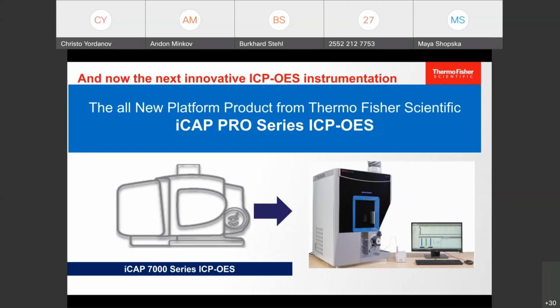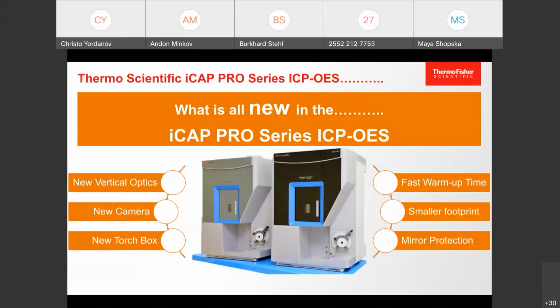And it's not evolution, this time it's revolution, because more or less all the parts inside of this instrument are new. We have a completely new optical tank. We have a new camera that's coming from astronomy. It's installed on satellites for astronomy research. We have a completely new torch box, with a super fast warm-up time. Without low UV, you can run after 5 minutes. To have the complete spectrum, including UV, you have to wait for 15 minutes. But I think for the whole spectrum, it's also the fastest startup time. It's the smallest footprint, and we have a fantastic mirror protection included.